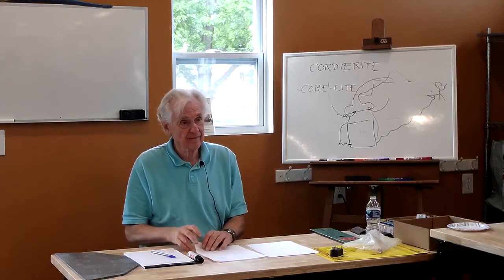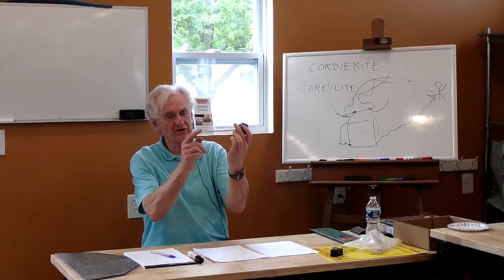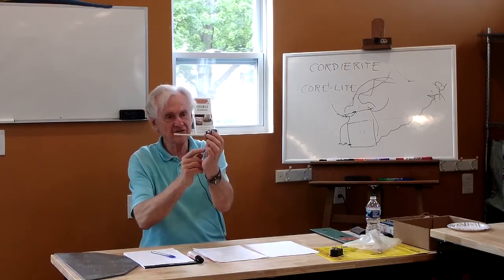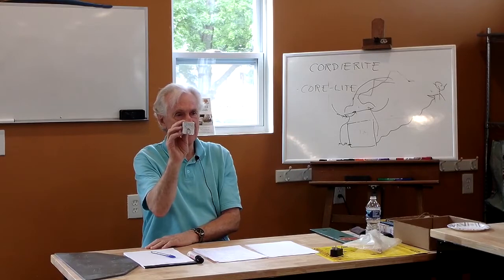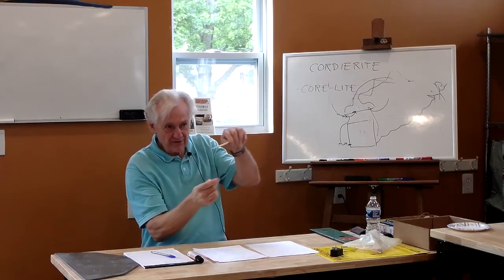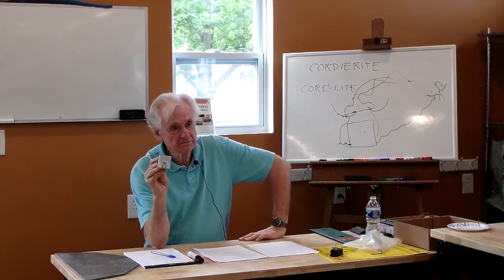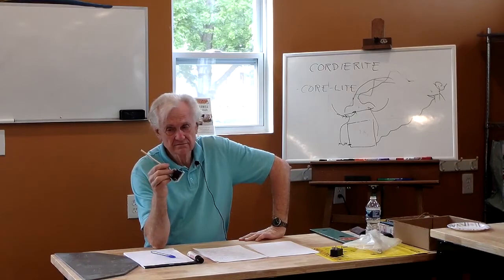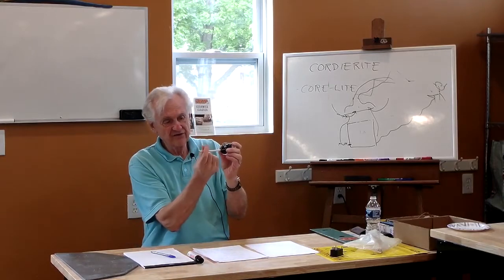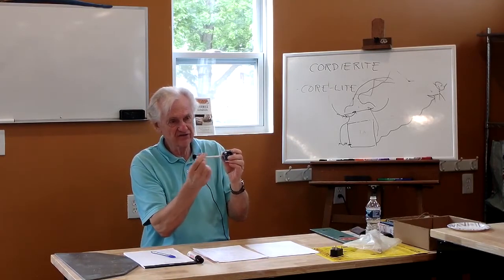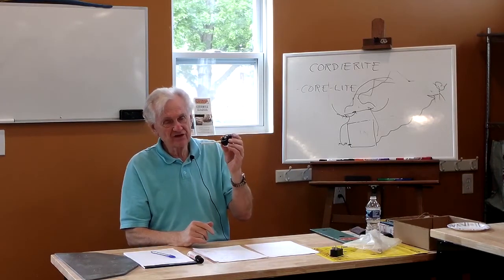What is that again? A pyrometer. Oh, no, the thing that you held up. Oh, well this is a little pyrometer, there's the thermocouple, this is a really simple one, it's a little thermocouple and I stick this through a hole in the kiln wall and I read the temperature on the dial, this is an analog and they make digital ones now that are more accurate and they're more responsive but they still have the little thermocouple you stick in through the wall only as a digital readout. So, do they make those so that ceramic coating doesn't like break off eventually like they always do? Well they have, the most, like the ones that I have now, the one that I have that's digital, it's portable, this is all, this is a metal, a high temperature metal sheath instead of being ceramic.